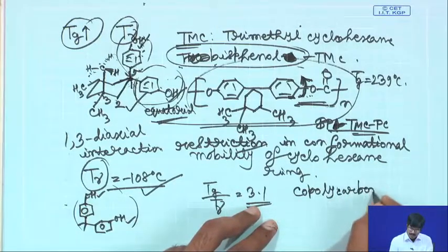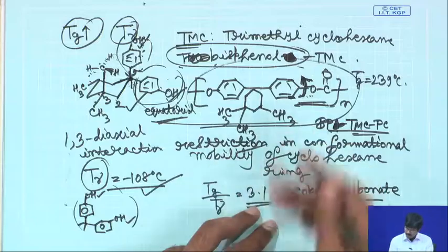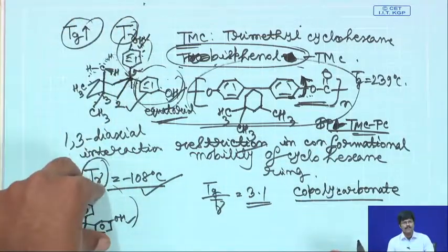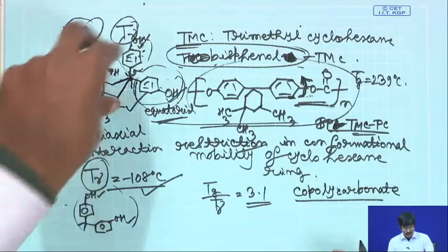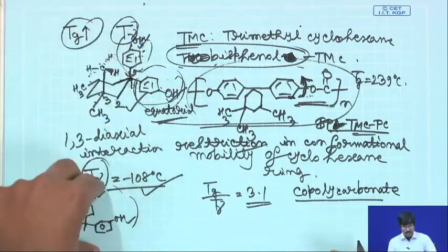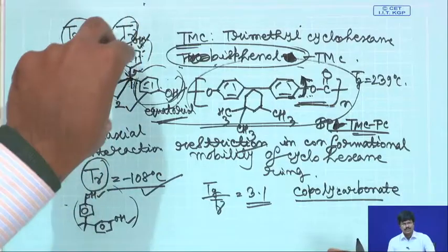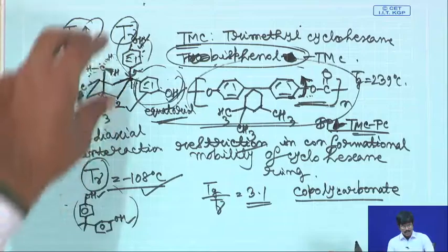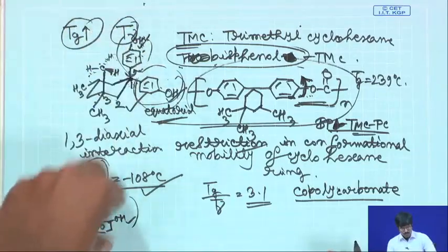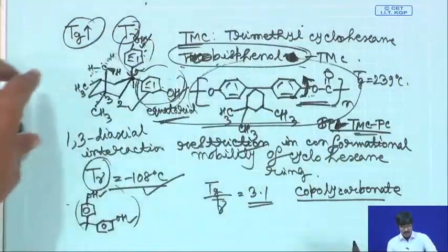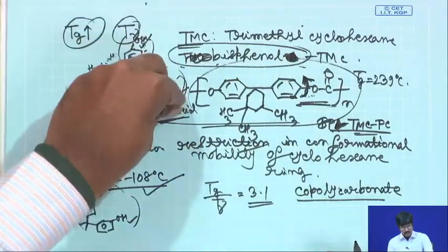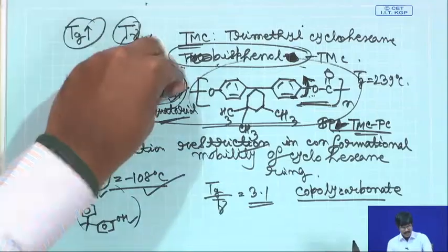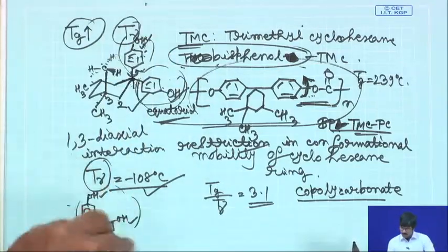So, you mix them together during the copolymer preparation, and then you will have both this monomer as well as this monomer present in the polymer, and you can change the relative ratio of them depending on how you start. Depending on the relative ratio of the monomers in the starting copolymerization mixture, you can introduce these two components in different ratios in this polymer backbone, simply because these phenolic OH groups here have very similar reactivity to the phenolic OH groups in this bisphenol A.